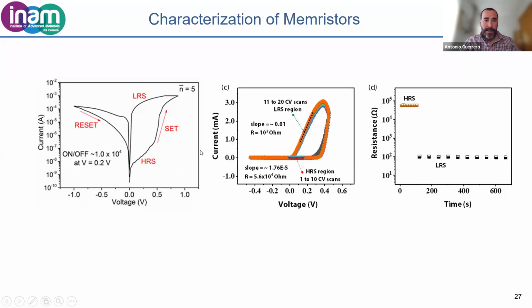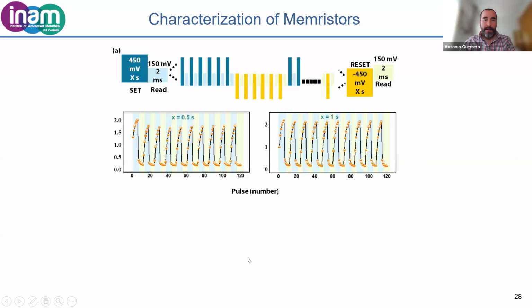So how do we characterize this? This is the same type of IV curve, but now it's linear. This is linear scale here and here. Here you see that this hysteresis is massive. So from the slope of this IV curve, we can calculate the resistance following Ohm's law. So this would be the resistance of the highly resistive state. And from the slope of this side of the curve, we can get the resistance of the low resistive state. Okay, so this is one way to characterize these devices.